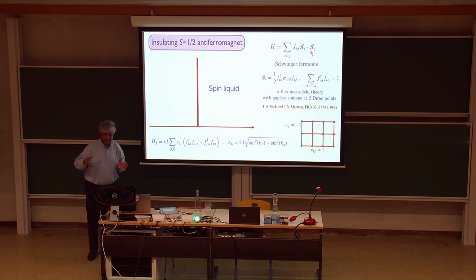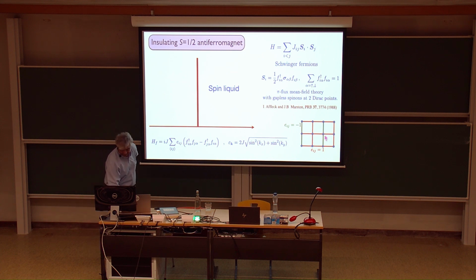I'm coming to that. The difference of this problem from other problems is that these fermions do not have any dispersion. Normally if I'm doing some density functional theory, I take in my interactions and renormalize some bare dispersion, I get a new dispersion. Here there is no dispersion, so I'm free to take any dispersion I want. It turns out the dispersion that works best is this dispersion shown here, where the green bonds are -1 and the red bonds are +1. So now if you look at the flux through every plaquette, it's -1. So that's the pi-flux state.